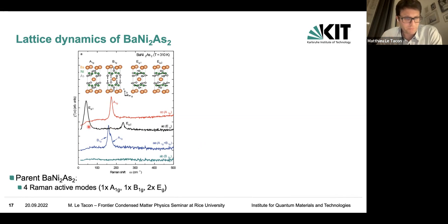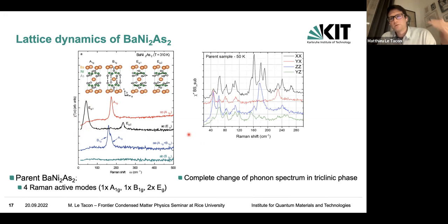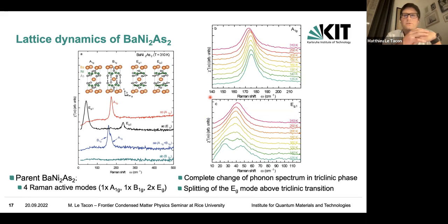So, just first thing, we note that the EG phonons are nice there, but somewhat already quite broad. That was a bit surprising, given that the quality of the crystals grown by Amir was absolutely excellent. But okay, we looked at this, and then when we cooled down the sample across the triclinic phase, then we have the commensurate charge density wave and the triclinic distortion, and then there are a lot of new peaks coming. So there's no doubt when you're in the triclinic phase, you're in the triclinic phase. That's clear.